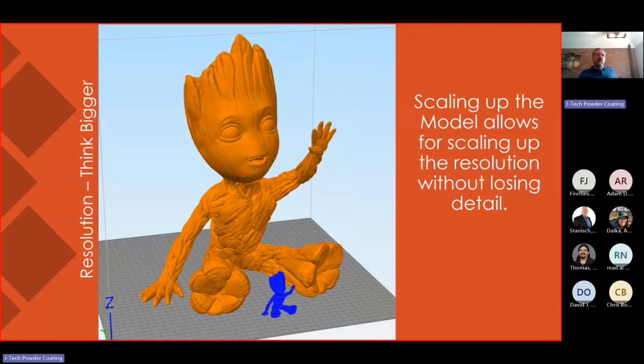Now, if you scale the baby Groot up 600% and the layer height were set to 0.6 millimeters, the details would be equivalent with the larger nozzle and layer height. And print time of this model would be about 36 hours.